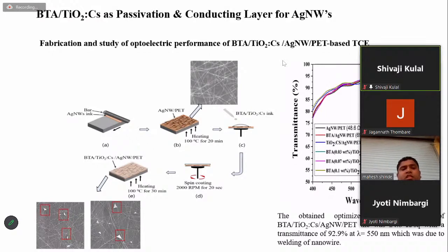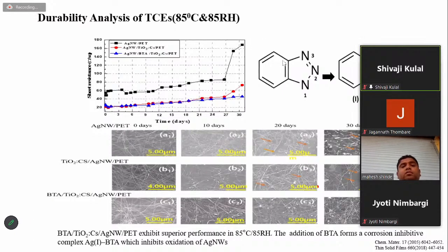With this transparent conductive electrode, I put it in the humidity chamber again and checked its stability for 30 days. We can see that for silver nanowire PET at 0 days, the silver nanowire looks good. But as days increase, at 10 days, 20 days, 30 days, there is oxidation of the silver nanowire, and we can see this damaged TCE.